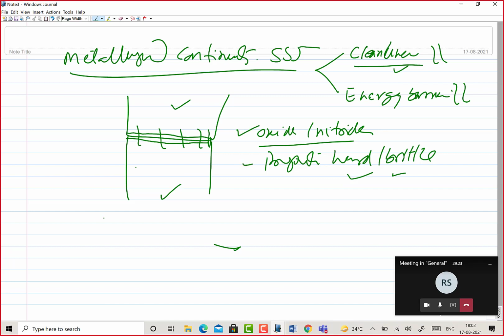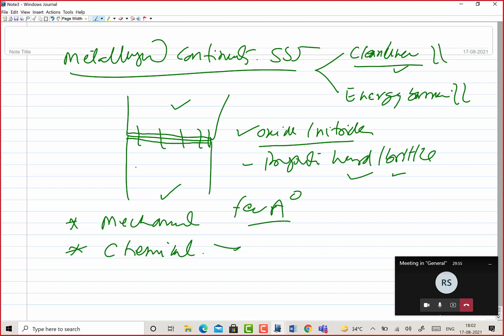So that is why just mechanical cleaning will not be good enough, because these layers are very thin, maybe a few angstroms, and very hard and brittle, especially oxides like those of chromium and aluminium. These oxides are very stable, very adherent, and very coherent with the surfaces, and they are very thin also. So just mechanical cleaning may not be good enough. You need chemical cleaning as well for removing all these impurities present at the surface. Sometimes in solid state joining, if interfacial deformation is involved, then that will inherently clean the surfaces and clear these impurities.